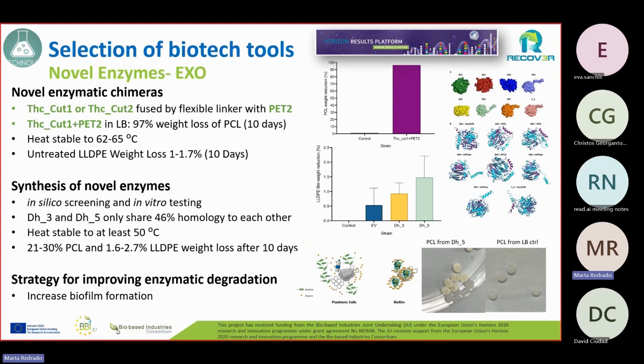Also, there was novel enzyme synthesis, thanks to in silico screening and in vitro testing. They were analyzing different microorganisms originally isolated from a fresh marine environment, and two of them, DH3 and DH5, which were also heat stable at 50 degrees, were capable of degrading polycaprolactone and LLDPE in 10 days.